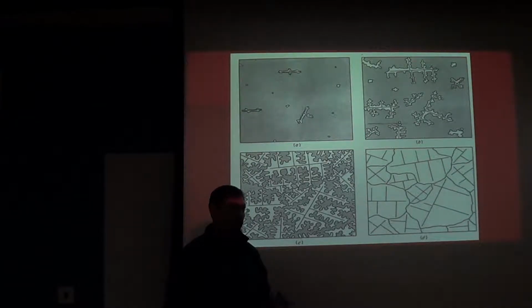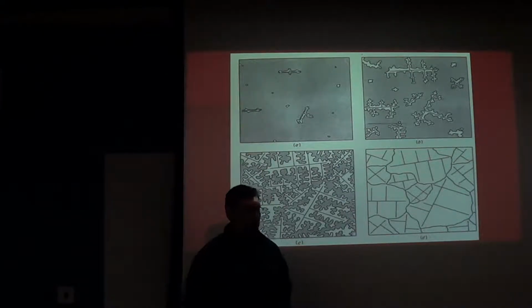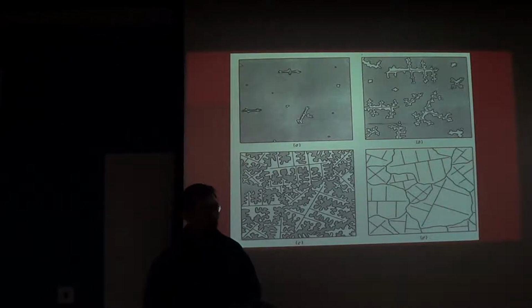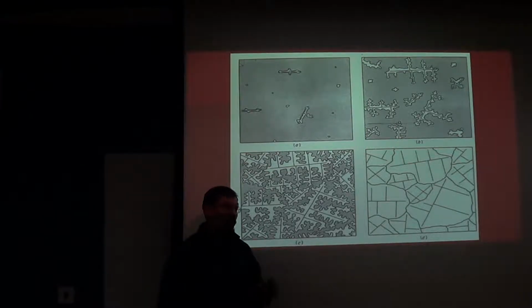Oh, okay. And so that's kind of what they were talking about there. You also have, in that particular material, very high carbon content, so you have iron carbides or iron complex carbides, depending on what little alloying elements they put in there. And so the carbides may still be present at forging temperature. In fact, they are in that case.